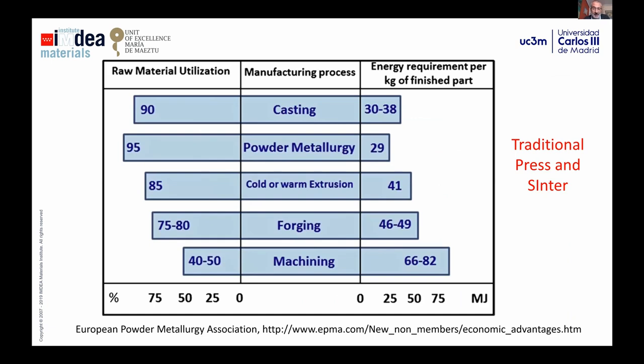If we go to the conventional press and sinter method, which is maybe 90% of the parts produced in the world by powder metallurgy, why do we have cheaper prices? Why is it a cost-effective production method? The main reason is that we use in the order of 95% of the raw material. We don't have any losses in material, or only a few losses, and we spend the lowest amount of energy to produce a final finished part, if we compare it with casting or extrusion or forging or machining. So we are combining a low cost in energy with a high level of raw material utilization. In that way, we tend to have lower prices.